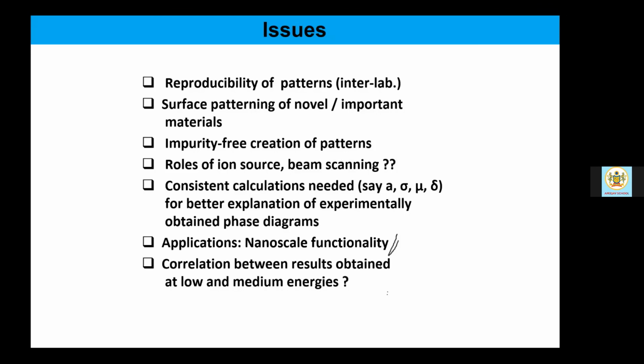Impurity-free creation of patterns is actually important. Otherwise, we may land up in very exotic pattern formation, which will be very, very difficult to explain. Okay, and the role of ion source is pretty clear, but beam scanning is not clear because in many of these results, particularly done at higher energies up to 30 kV, 50 kV, 60 kV, the beam was uniformly scanned over the surface to reduce the completion time of experiments.